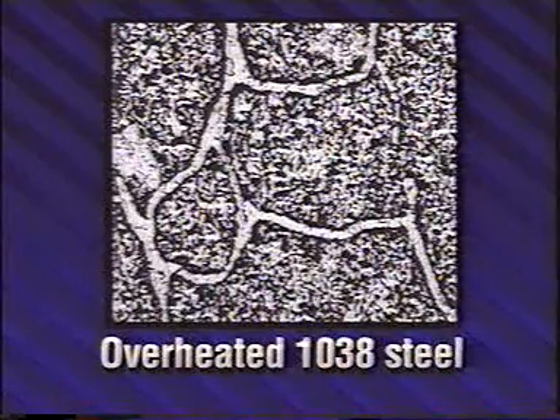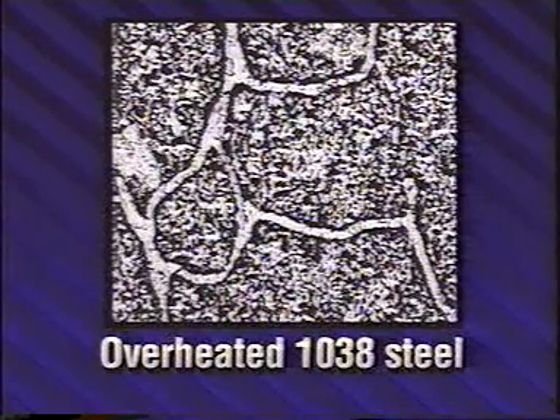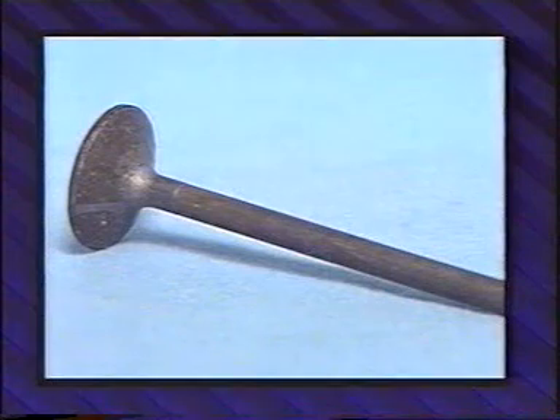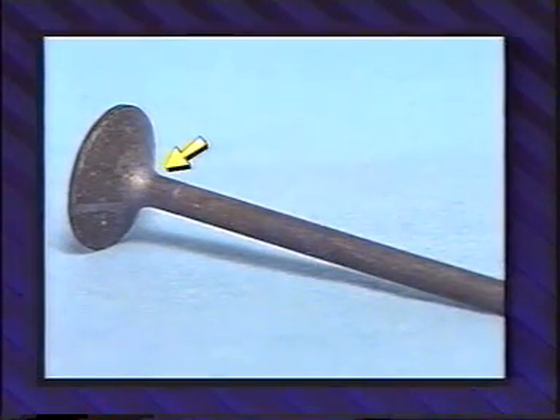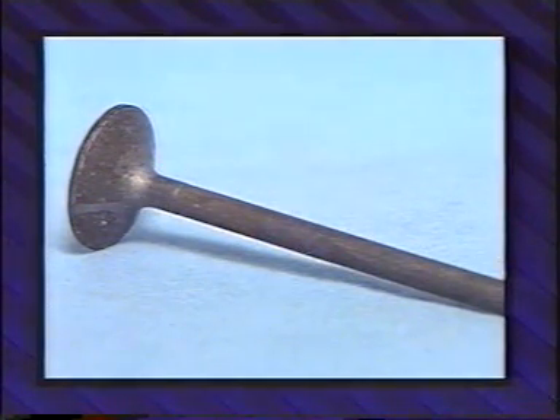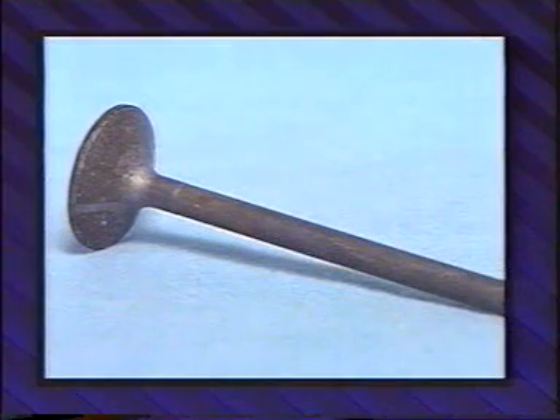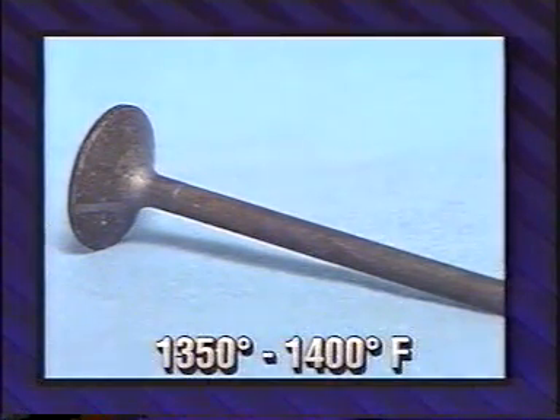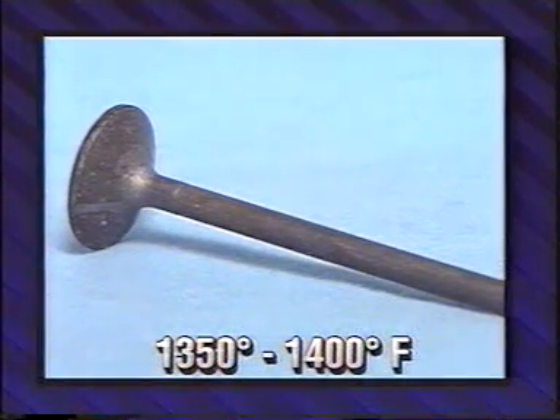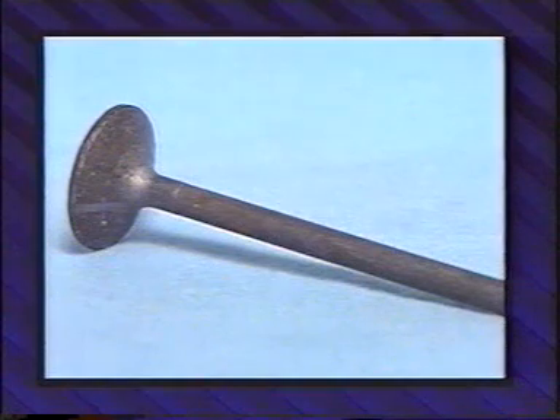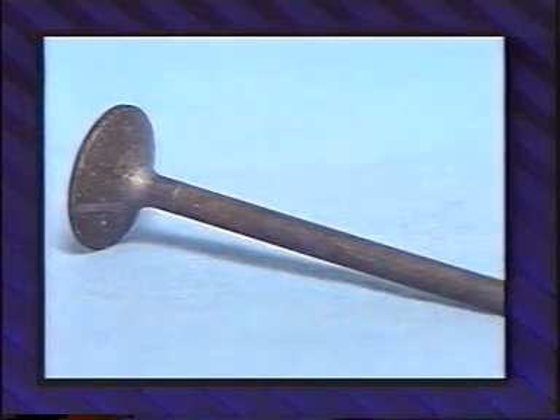Burning is the most common mode of valve failure. The burning results in large grain size and oxidation of the grain boundaries. The next most significant failure mode is fatigue. Fatigue generally occurs at the junction of the stem and head, the point where hot gases from the combustion process impinge on the valve stem during the exhaust cycle and create a notch effect. Temperatures in this area normally range from about 1350 to 1400 degrees Fahrenheit. Mechanical forces from firing pressure and valve spring pressure provide the stress for failure.